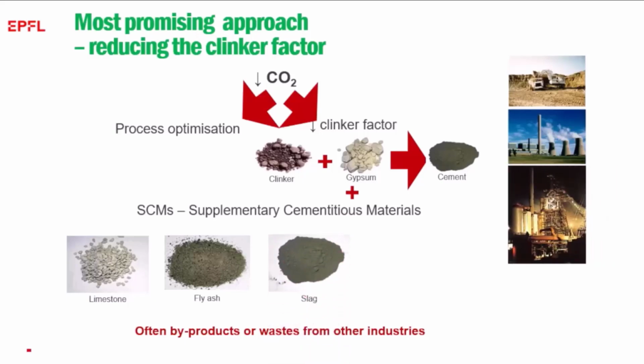Slag is coming from producing steel. And again, that's a very energy-intensive process, something like 10 times more energy-intensive than producing concrete. And even today, the amount of blast furnace slag we have available is just about 8% compared to the production of cement. And so even now, 95% of blast furnace slag is already used in cement and concrete. If you specify high slag levels in your project, you're just taking it away from another project. And globally, in terms of the world, which is what matters, you have no net reduction in CO2.